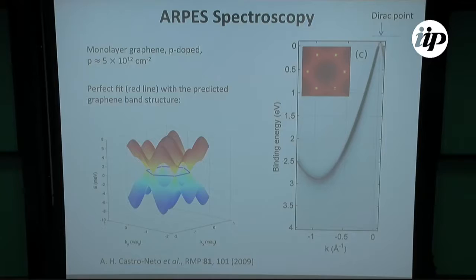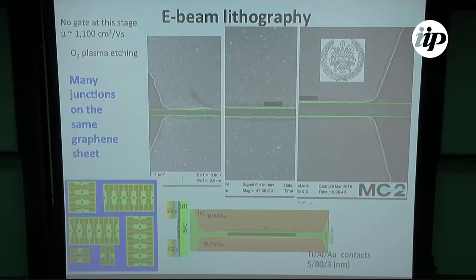What you see by ARPES is that this graphene is P-doped. The reason is because if you follow this K vector line here in the spectrum, then you see the band, and that is the Dirac point up here, so that you have some P-doping in the sample. And then, by electron beam lithography, you can build many junctions on top of a single layer of graphene.